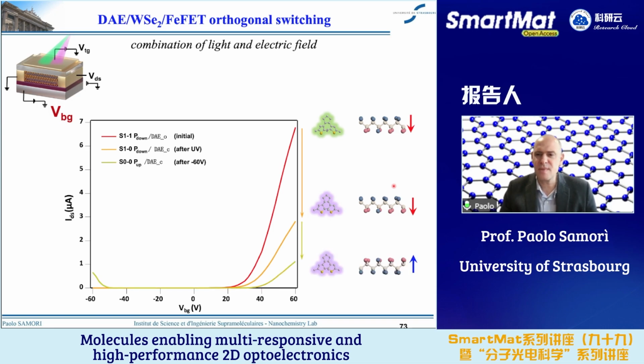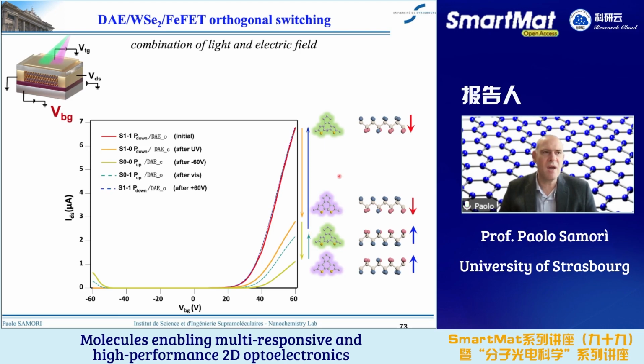And you can see the current, that we have further depleted the electrons in the channel. And so at this point, we have the lowest current possible. Then at this point, we use visible light to switch the diarylethene from the closed to the open state, and we recuperate a bit of the current. Then we apply a plus 60 volt, and we go back to the P down state. So this is completely reversible. You can see that we can use, let's say, in an asymmetric manner, the two inputs.